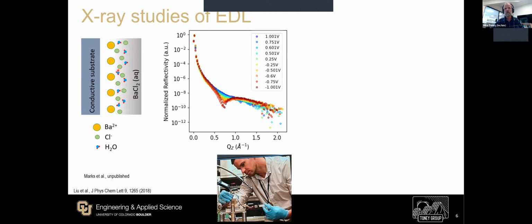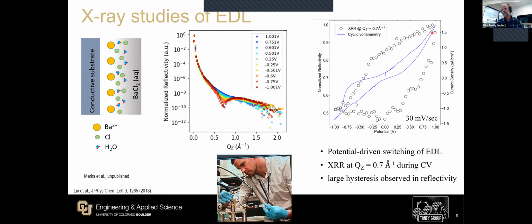These data are quite new, so we don't quite have a complete picture of what's going on here. But what is interesting, and frankly I don't think we completely understand, is this: if we hold the potential and collect the reflectivity, sitting at one incidence angle and reflected angle, and then record the reflectivity as a function of potential as we do a cyclic voltammogram, this is what we get. The blue is the CV, the current density measured over here. There's a bit of a slope, but you see largely, although not completely, capacitive behavior. And then the dots are the background-subtracted X-ray intensity as we move down this way, and then move back this way.